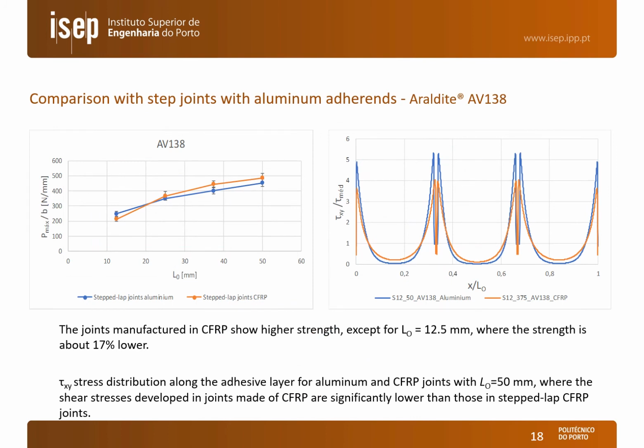Next, we are going to compare the obtained results with joints with aluminium adherends, and we can see the strength results in the graphic to the left, and we can see that typically the composite joints have a higher strength than the aluminum joints, and the reason for this is that the composite is stiffer, and so the peak stresses are going to be smaller, and we can see this in the stress plot to the right. The only exception was for 12.5 millimeters, but here the lower strength of the composite joints was caused by the interlaminar failure, which weakened the respective joint and made the result smaller than the one with aluminum adherends.